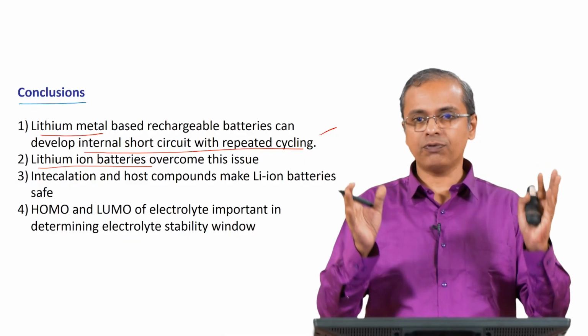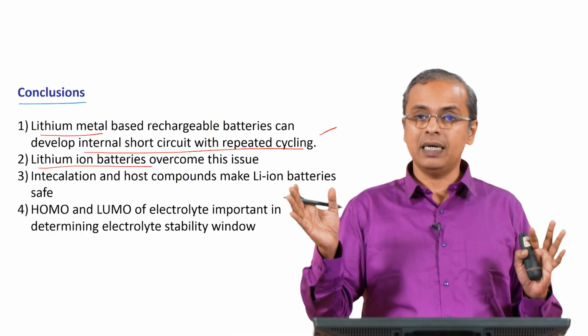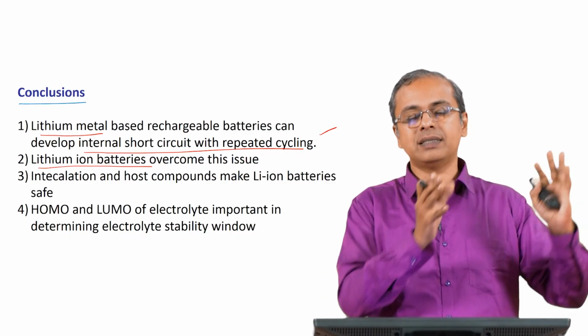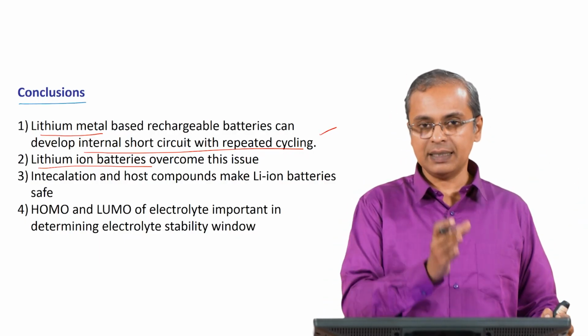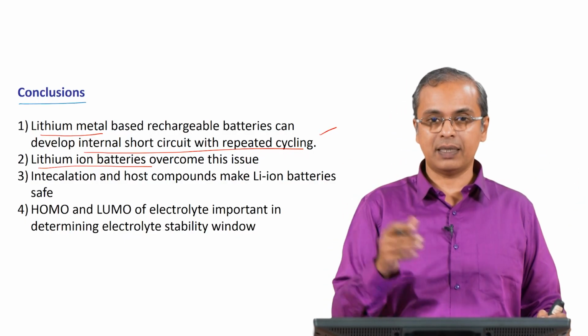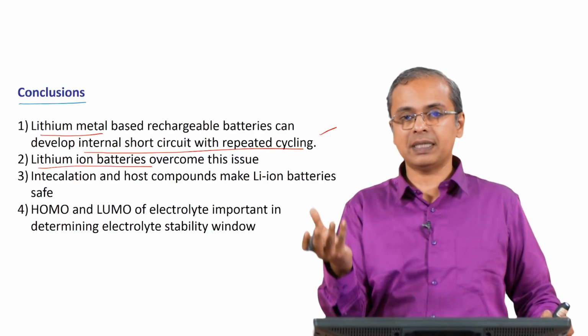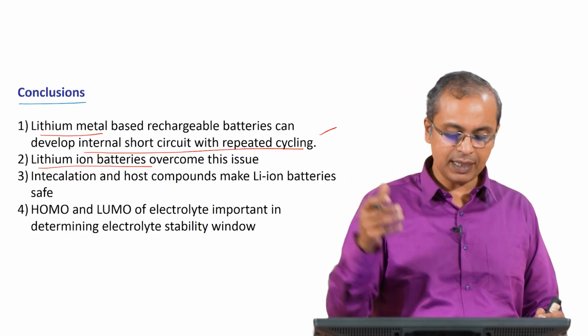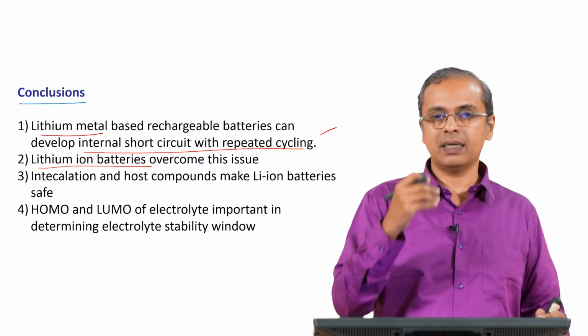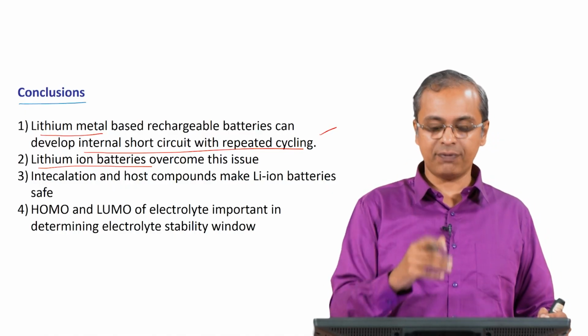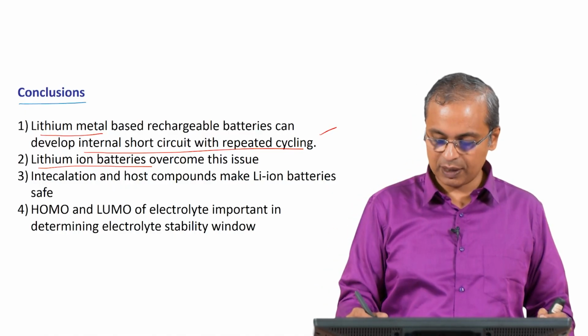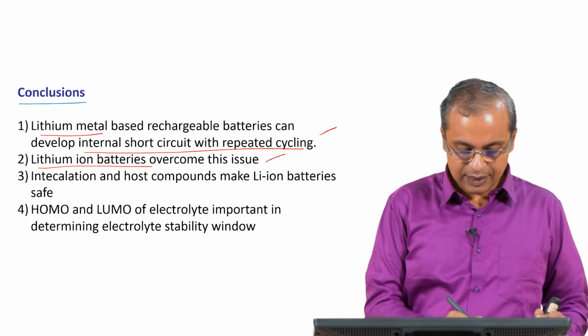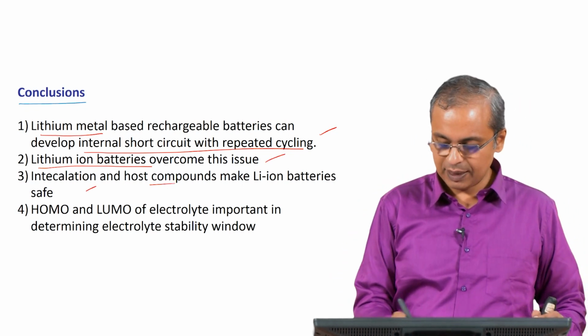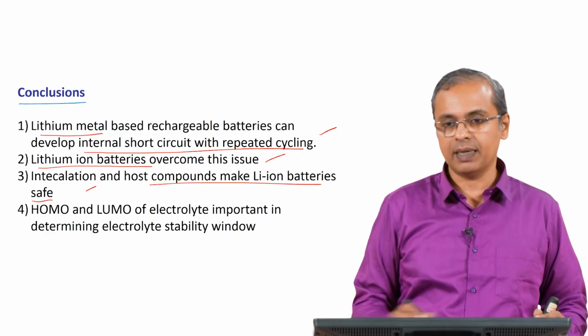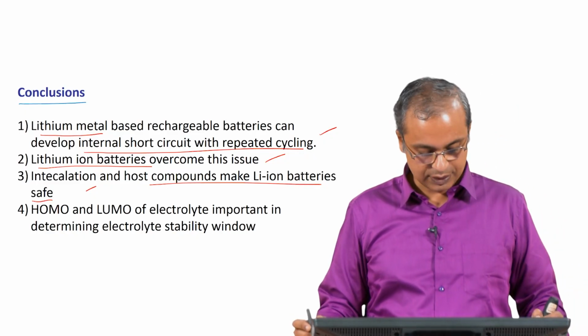So, they do some careful mass balancing to ensure that lithium is exhausted, but there is still a little excess carbon available, right, because LiC6 will form, you should not have more lithium than that. If you send more lithium, then that lithium will start plating on top of graphite, we do not want that, we will just keep a little less lithium than possible to be held within that graphite, and on that basis we overcome this plating issue. Intercalation and host compounds make lithium ion batteries safe, so that is the idea that we explored in some detail,